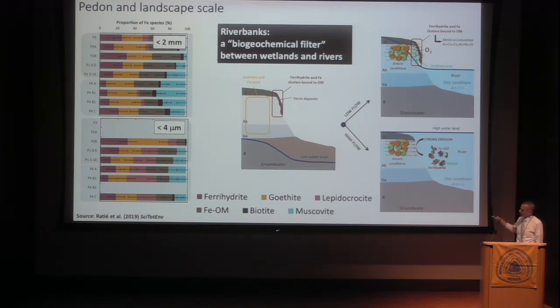As those changes are occurring, trace elements, particularly contaminants that are moving through the wetlands into this system, are starting to be accumulated, but in ways that are controlled by the mineralogy. So, for example, the iron oxides would accumulate arsenic, the organic matter accumulated lead, and then cobalt, copper, and nickel could be accumulated by these iron-organic matter complexes.